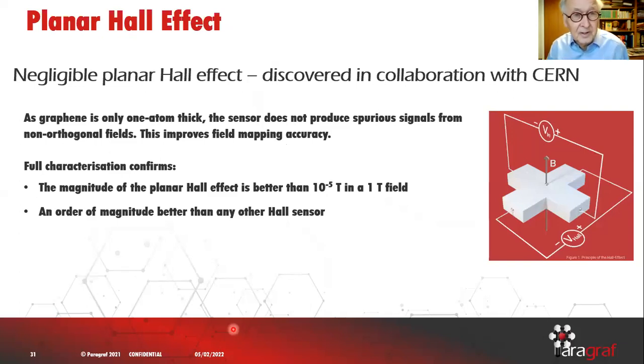This is another interesting effect, called the planar Hall effect. We actually discovered this when we had some of our devices tested by CERN. Graphene is only 1 atom thick, whereas the other Hall sensors, even quantum well Hall sensors, have a finite thickness. This produces spurious signals from fields which are not orthogonal to the plane of the sensor. If you have no planar Hall effect, this improves field mapping accuracy, and this is something CERN are particularly pleased about.